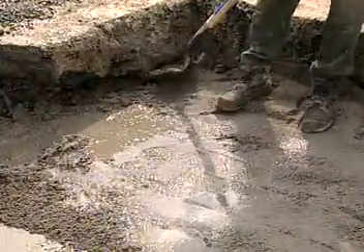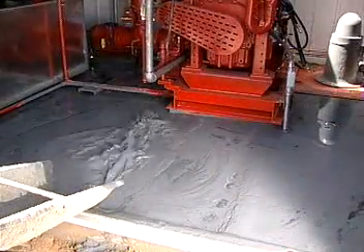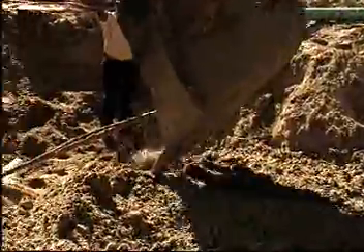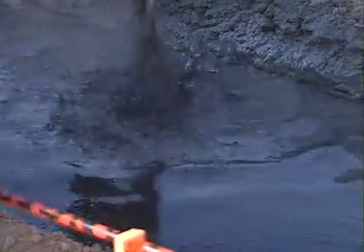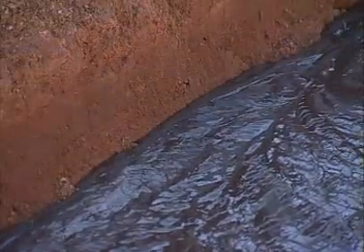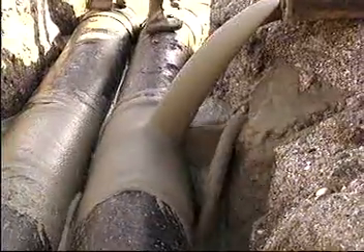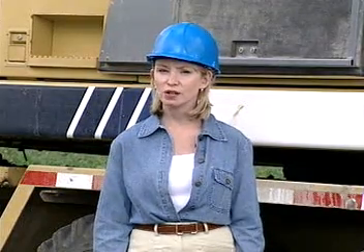Flowable fill mixtures can be designed to range in permeability from that of a uniform coarse sand to that of a clay material. This versatility in design offers numerous advantages over local site material and does not limit the engineer. Flowable fill mixtures are typically designed to reach a unit weight between 70 and 145 pounds per cubic foot. The use of special flowable fill admixtures can reduce the unit weight to as low as 20 pounds per cubic foot. Flowable fill mixtures offer numerous advantages when stringent design criteria must be met.